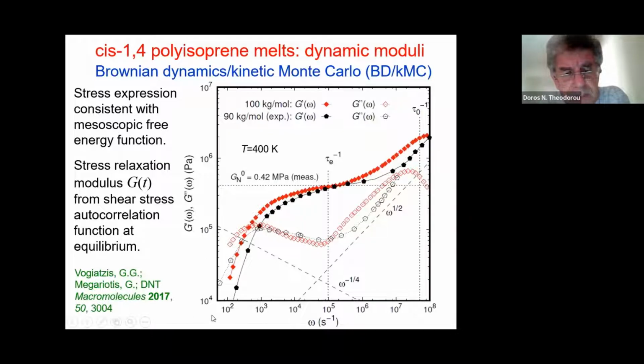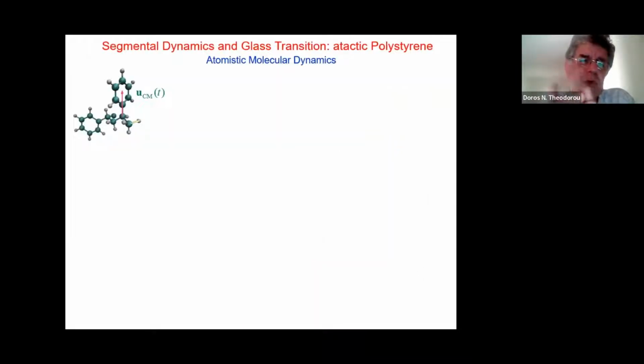You see that the frequencies here are on the order of 100 inverse second. These are very long time scale phenomena that could not conceivably be captured by a molecular dynamic simulation at the atomistic level. However, the mesoscopic simulation can get them. Now, one is also interested in the so-called segmental dynamics of polymers. This is the local dynamics that is frozen when the system becomes glassy.